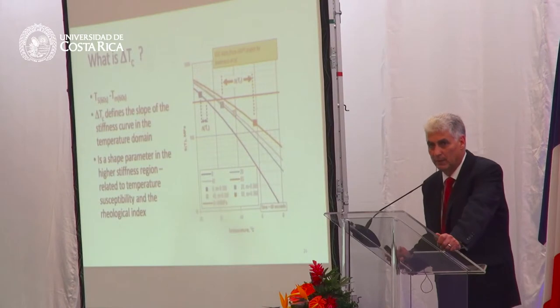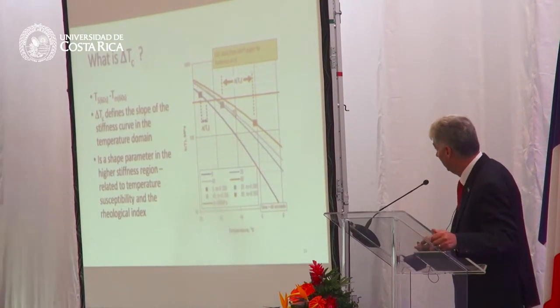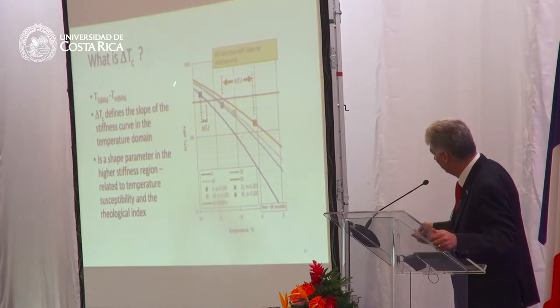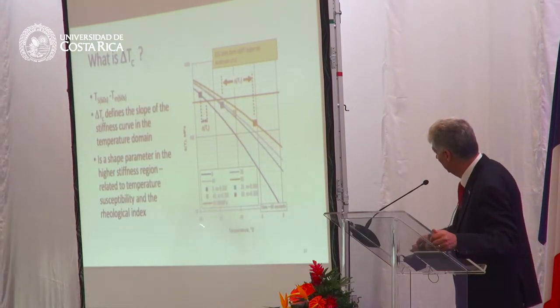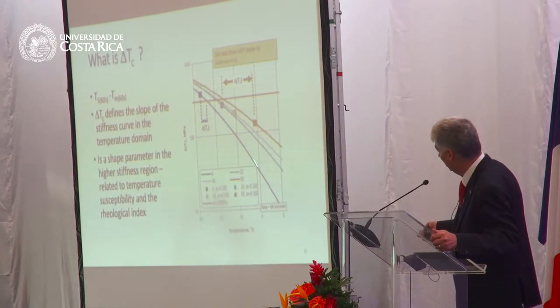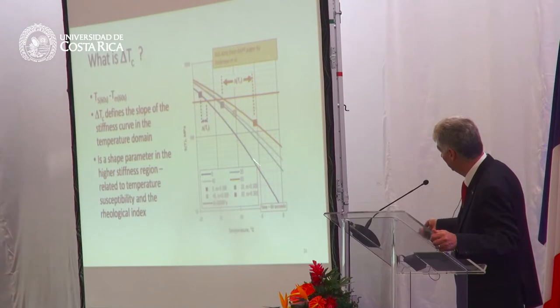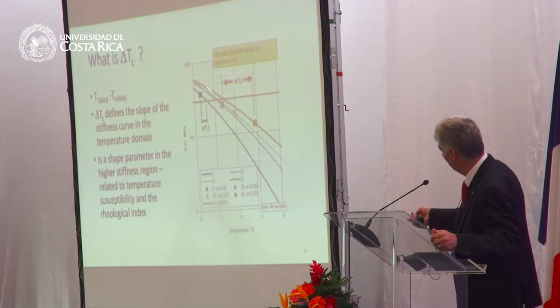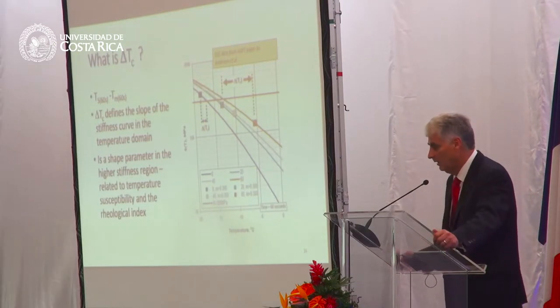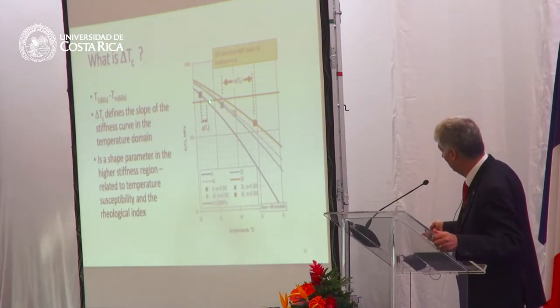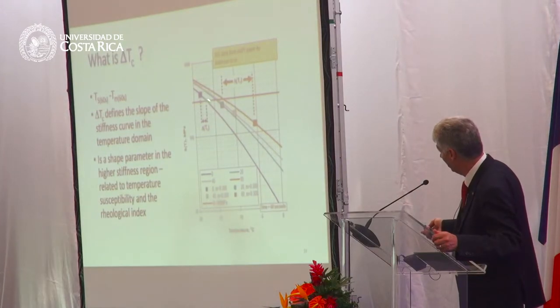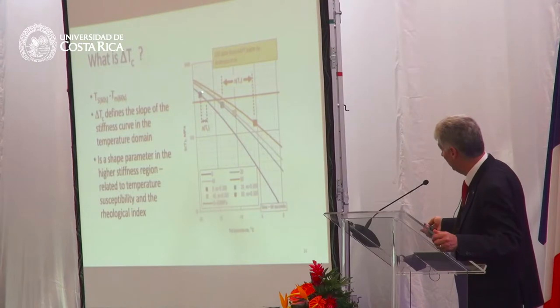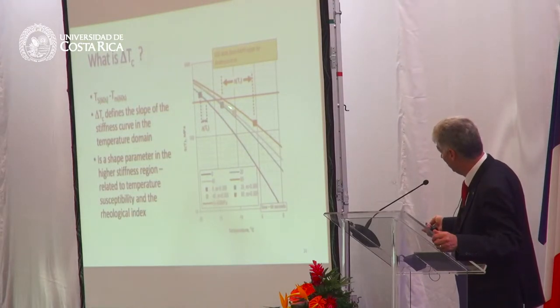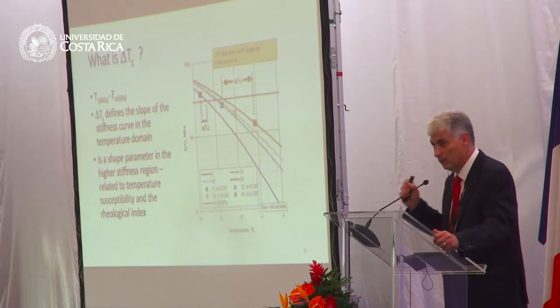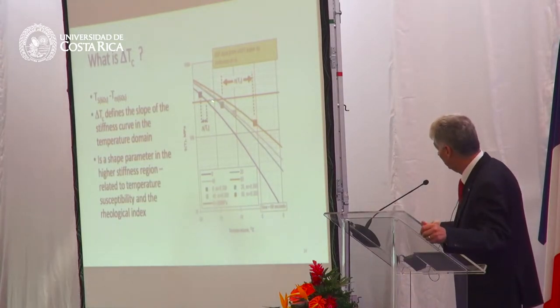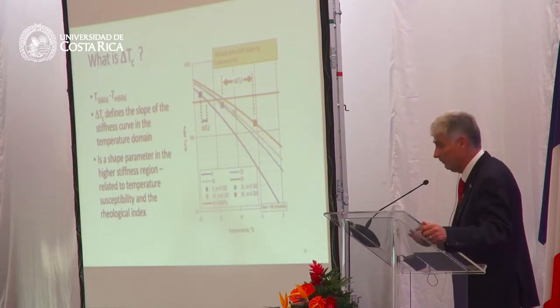So delta TC is from the bending beam rheometer. And what we do in the bending beam rheometer, let me explain the graph. This is the stiffness on the vertical axis, temperature on the horizontal axis. The four curves here represent different aging conditions. This is an unaged material, and this is 80 hours in the PAV, 20 hours, and I think 40 hours in the PAV. And if you take the temperature at which you have the stiffness of 300 megapascals, and deduct from that the temperature where the m-value equals 0.3, so these square boxes here represent where the m-value was 0.3, and if you deduct this number from this number, you have the delta TC.